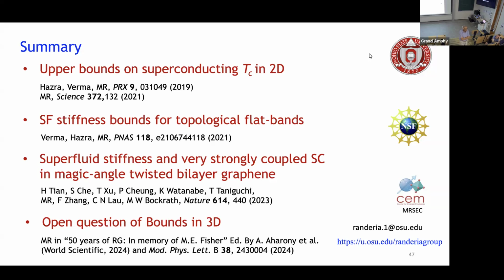Order parameters can be quite difficult to measure. For instance, in helium-4, it's very hard to measure the order parameter. You can now do inelastic neutron scattering to find how many bosons are in the condensate, but it's not an easy experiment to do. Or in superconductors, other than the Josephson effect or something, it's very hard to measure the order parameter per se. Delta is the amplitude of the order parameter, so it's easy to measure the gap.